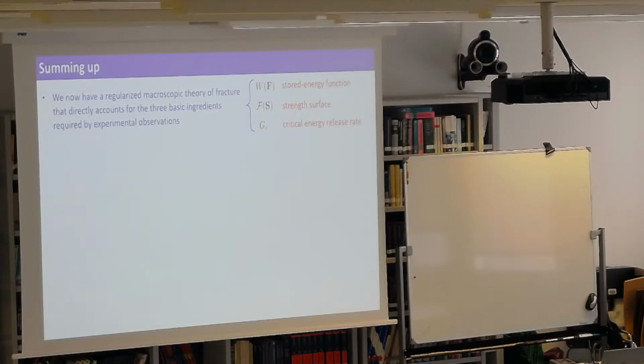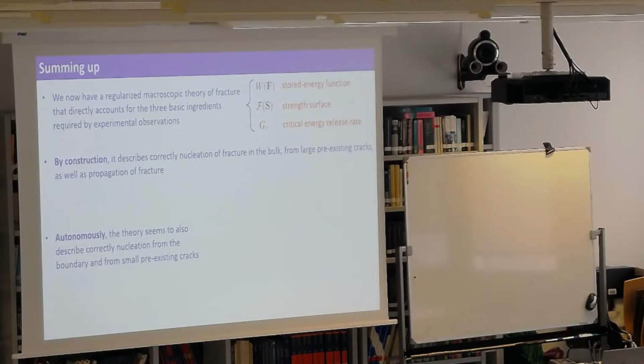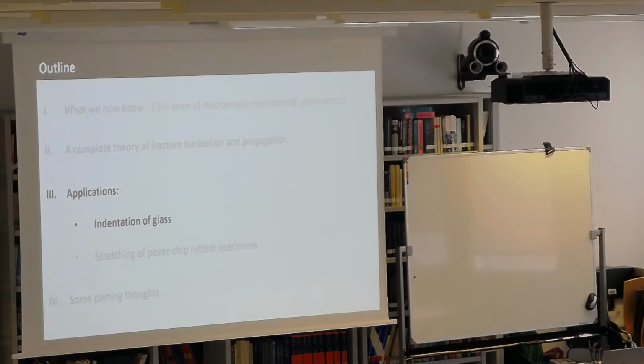But summing up, what we have now is a regularized theory of fracture that accounts for all the 3 basic ingredients that are required from experimental observations, and that by construction, it's going to give you the right nucleation in the bulk, and the right nucleation and propagation from pre-existing cracks. And autonomously, and this we do not understand, we simply observe it, we do not control the transition zone. The theory does the transition by itself in a way that seems to be consistent with experimental observations. So remember what we control, the input is this value and this slope, if you like, right? The rest we don't control. That's the transition zone. Autonomously, these equations, magically, seem to be describing what happens, right? And that, I think, is remarkable. And there's something magic about these equations. All right, so applications. How am I doing?